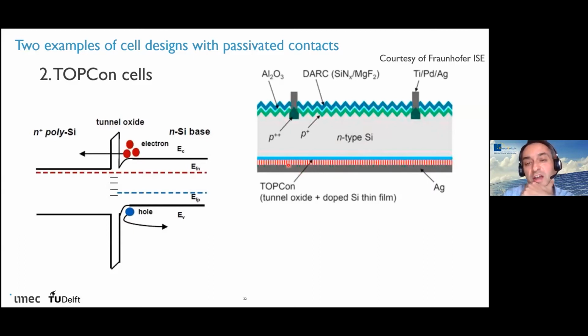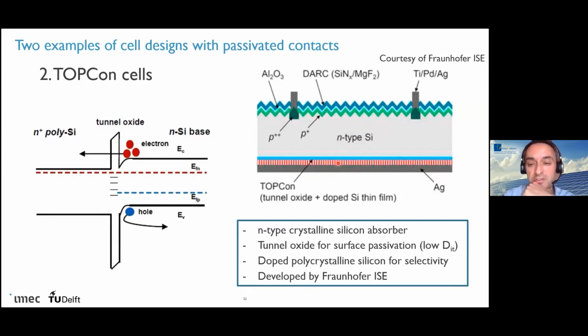On top of that, you have a doped polycrystalline silicon layer that gives you the back surface field, and then you have the metal. Again, the surface of the silicon is not in direct contact with the silver at any place, because you always have the tunnel oxide and the polycrystalline silicon layer in between. This is not only a passivated contact, but also a selective contact—this type of contact will typically attract one type of charge carrier, for instance the electrons, and repel the holes, or vice versa.